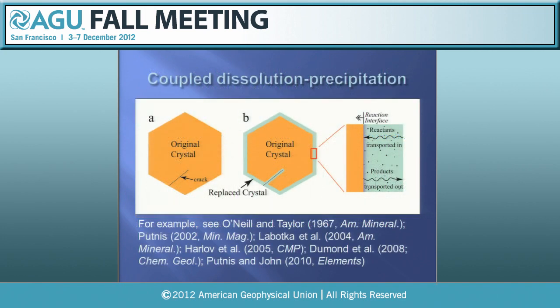And the idea here is that you have an original crystal, maybe cracks in it, and then there's a reaction interface that starts on the outer rim of the crystal and then moves in. It replaces the original crystal by a new reaction product, and it propagates inward because the replaced material has a nanoporosity or a microporosity in it. And that allows reactants to diffuse in and products to diffuse out. I suppose they could flow in and out too. But anyway, they can get in and out, and that nourishes this reaction interface that moves inward into the crystal.